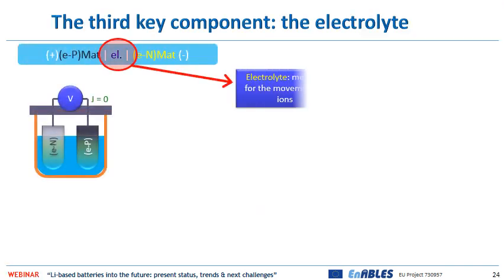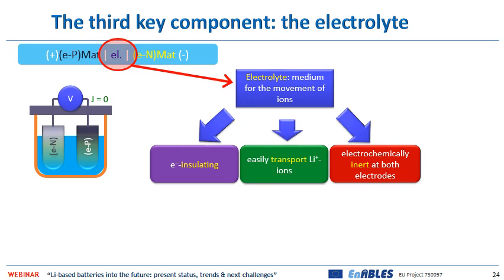In a standard lithium-ion cell, the third key component is the electrolyte. In general, an electrolyte is a solution of lithium salt dissolved in a mixture of organic carbonate-based solvents. This solution is soaked in a membrane which physically separates the electrodes and prevents short circuit. The electrolyte allows the lithium-ion transport between the electrodes. It should be electron insulating and electrochemically inert in combination with both the electrodes.